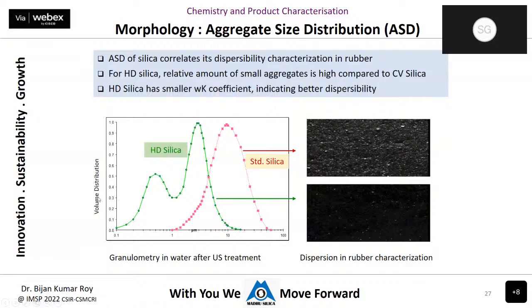So here is the volume distribution, and here is the size. If we scan these two silicas, we will find that the highly dispersible silica has a bimodal distribution. To measure this particle size, you need to apply some sonication or some shearing force. It is a standard method. This is similar to when silica is being mixed into the rubber in an internal mixer, because there is a shearing force by which the silica particles can be disintegrated.